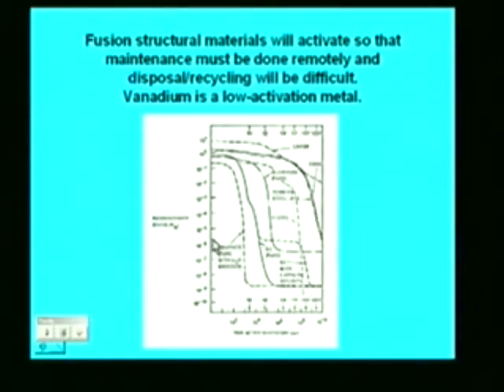Hands-on level for recycling these is probably around 10 to the minus 6. But notice vanadium, I can find it. Here we have a vanadium alloy, vanadium 20% titanium. And if we go out here to 10 years and beyond, we're orders of magnitude below stainless steel. So if you have a structure like a fusion reactor made from vanadium, then at the end of its useful life, you have a chance of recycling it, or at least if you have to, burying it. Recycling is favored.